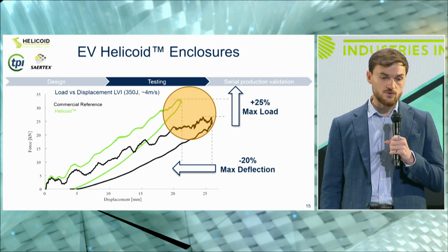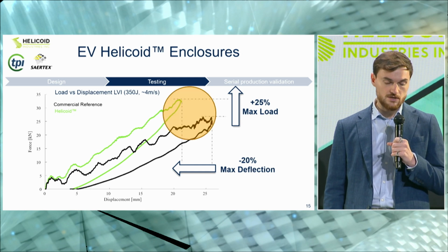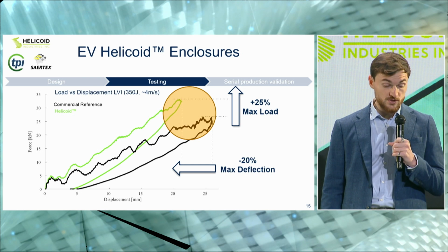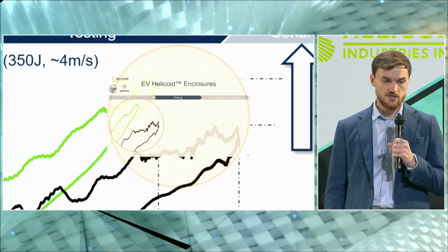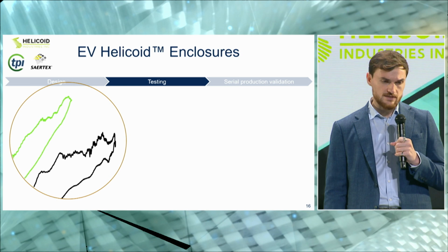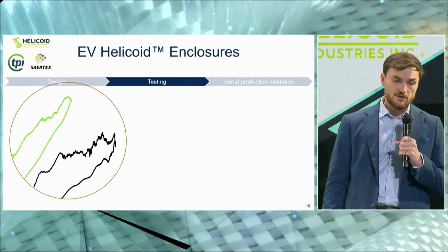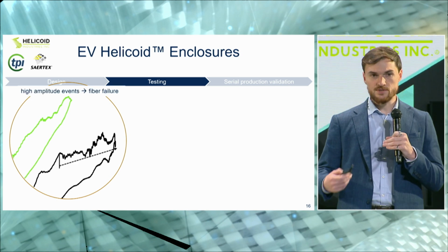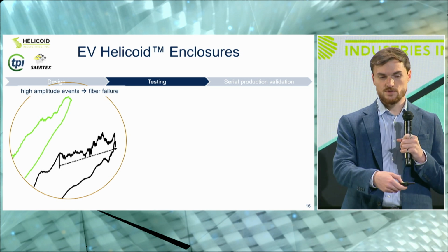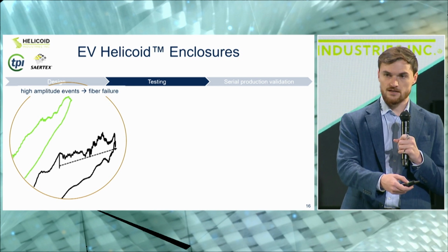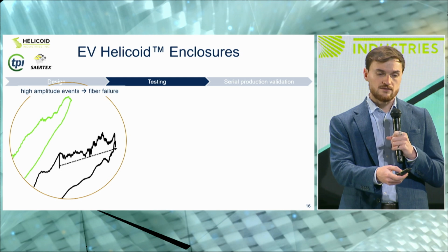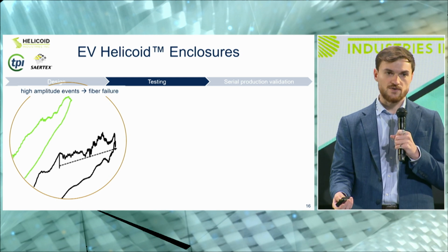In fact, if you look closer to the point of maximum load in the structures, you can see that there is a clear difference. And in the reference, you can notice high amplitude events. Now, if you are familiar with this type of test and data, you would know that these high amplitude events are associated to fiber failure.